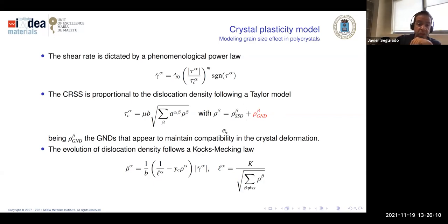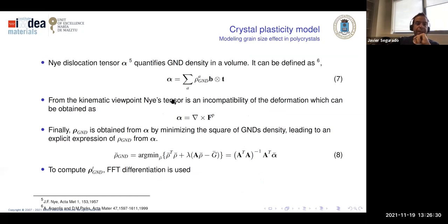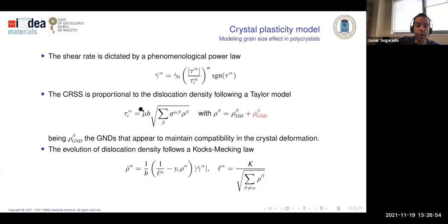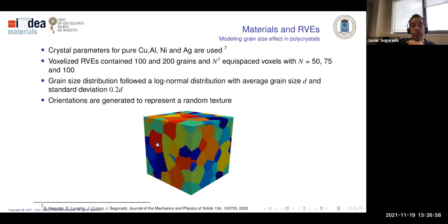The evolution of the SSDs follows an ordinary differential equation, the Kocks-Mecking law, with creation and annihilation. But the second part, the GNDs, is something purely geometrical, because what these GNDs cause in the crystal is a type of curvature. This curvature can be expressed very well by the Nye tensor, which can be obtained by computing the curl of the plastic deformation gradient, the one that we have in this intermediate configuration. So if we can measure this from the FFT simulation field, then we can obtain the density of GNDs as a result. We can put it back in this equation and we have the hardening effect. We can do everything within the FFT code.